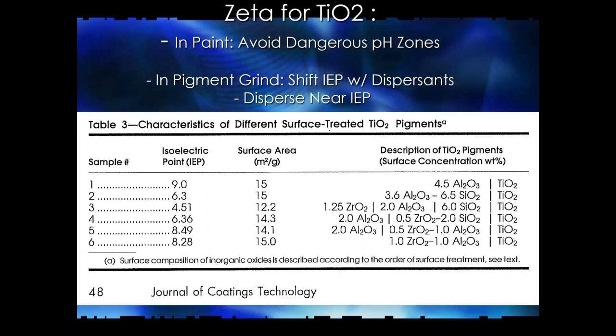Now, when we look at TiO2, you'll find that even the exterior grade, semi-durable or durable products all have different levels of alumina and silica and zirconia, different percentages. And you say, whoa, do I have to use different dispersants for each of these? Well, fortunately, there has been a process of natural selection. The dispersants were made for the TiO2. The TiO2 was made to be compatible with the resins. The resins were modified to be compatible with the TiO2. And this whole process goes back and forth until you optimize for somebody's dispersant and somebody's resin.